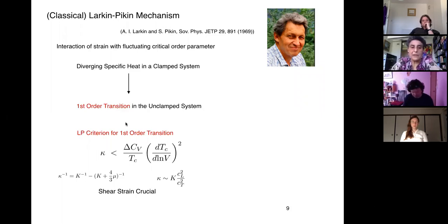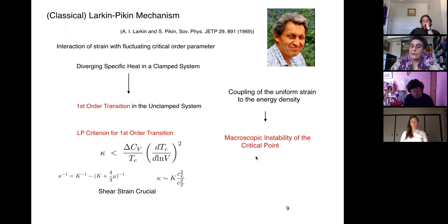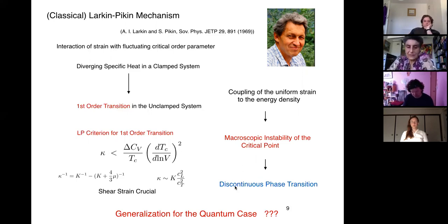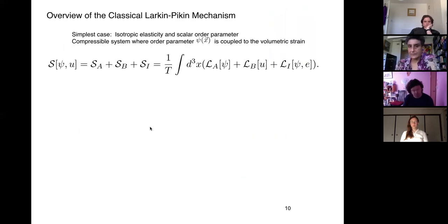And you see the appeal of this because we know in barium titanate, when it's clamped, it has a diverging specific heat, and we know that the unclamped system is first order. So what Larkin and Pikin said was that coupling of the uniform strain to the energy density leads to a macroscopic instability of the critical point, which leads to a first order transition. And so the natural question we asked ourselves was, can we generalize this to the quantum case? In order to generalize it, we're going to have to study the classical Larkin-Pikin mechanism a little bit, because we have to reformulate it in such a way that we can generalize it to the quantum case.